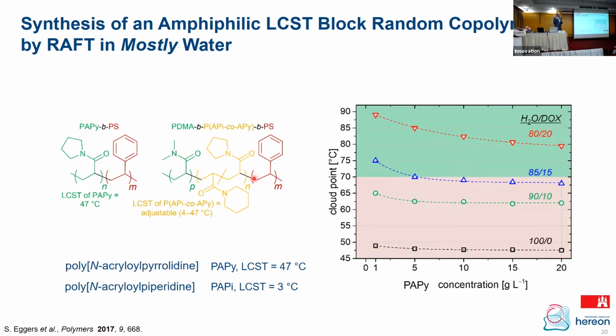And the aim, the strong motivation, was to get rid of anionic, and we must find a way to get this polystyrene polymerized, also not with anionic, but with RAFT. And here you see Stefan's initial work in this direction. I'm not showing much about it because this is also a nice story and has a good continuation. Styrene is a difficult monomer, and RAFT polymerization has its difficulties. So everything here is thermally initiated RAFT.